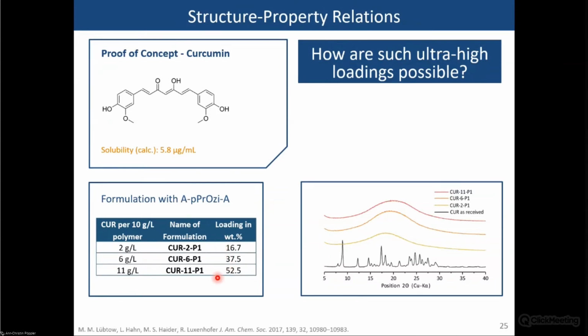So we have 3 different forms: low, medium, and high loading. And you can see here on the right that in the colored diffraction patterns, all of them are X-ray amorphous. So we cannot get detailed information like for the crystalline material. And this means we can study these amorphous systems, but with the question in the back of our mind, why is it possible that they can load up to more than 50 weight% of such additional compounds.